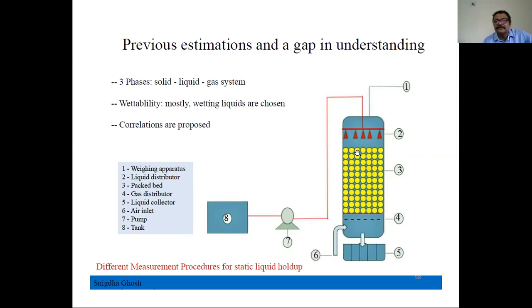There is also another interesting thing. Suppose I have liquid coming here and the gas is going from the bottom. I suddenly stop the gas flow as well as the liquid flow. What will happen? The liquid will drain, but not all of it, because of surface tension, some liquid will remain between the particles. This is called static holdup in chemical engineering, and in the blast furnace also we call it static holdup. Why is it important in the blast furnace? I'll tell you why. In the blast furnace, the slag is much more viscous and its interfacial properties are different. Actually, most of the slag reaches the bottom through static holdup.